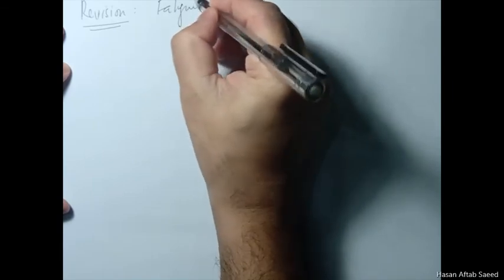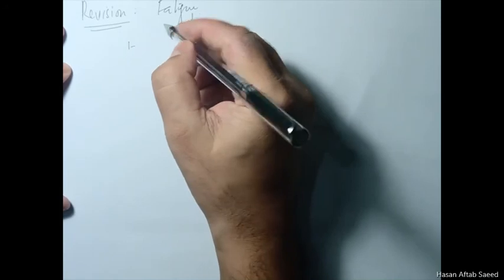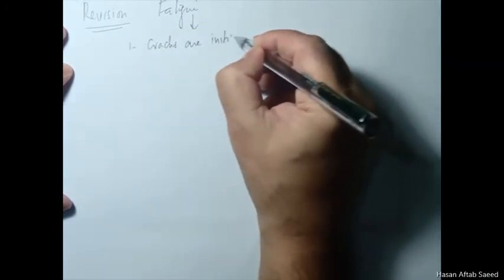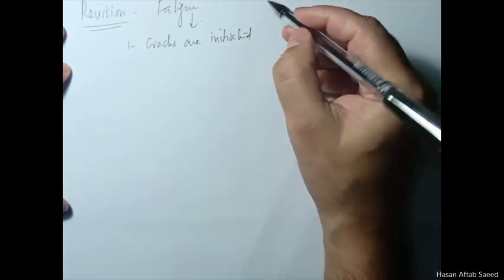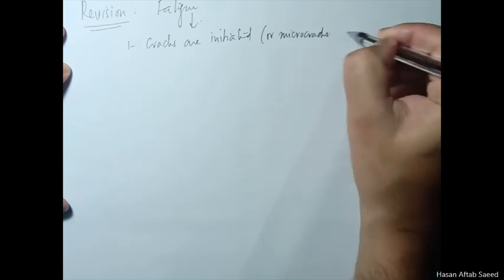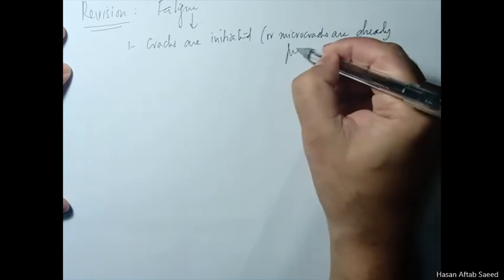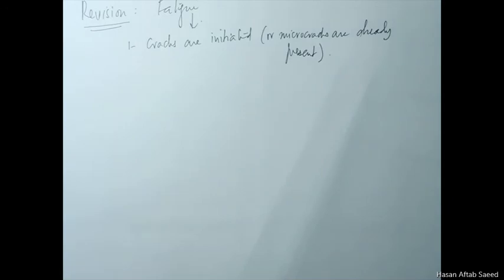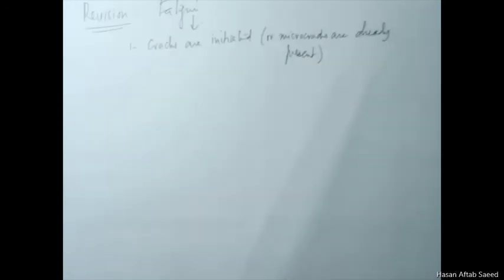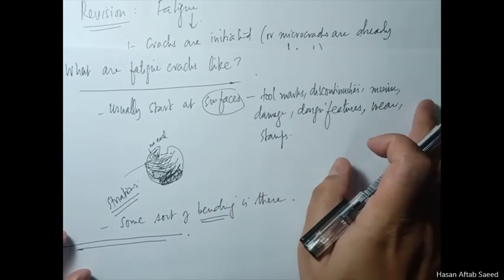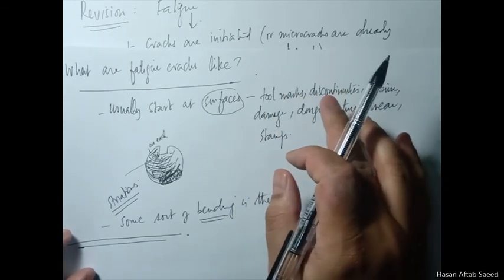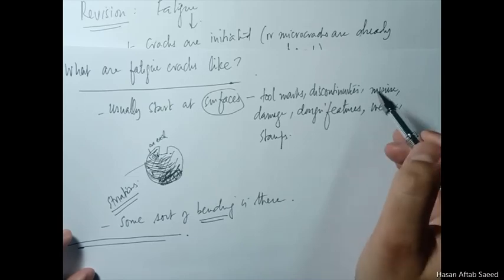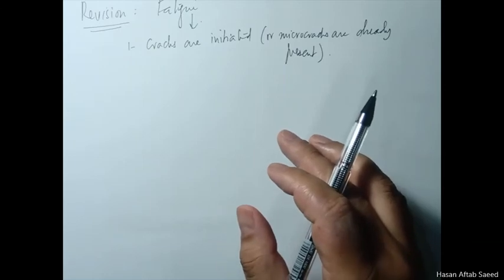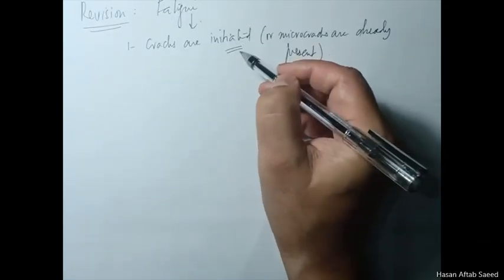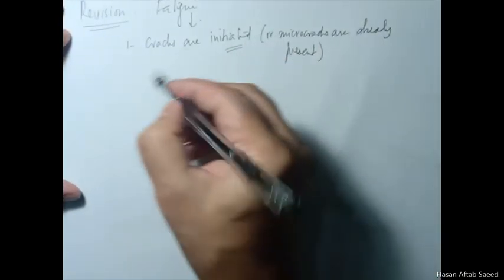What is fatigue? Where does it fit in? Fatigue. The process is something like this. Cracks are initiated or micro cracks are already present. All materials will have some sorts of micro cracks or defects. So cracks are already there, but even if they are not there, we have just discussed that even if something is perfect, no cracks, you have polished it, still at some discontinuity, at some design feature, at some point during use, if not during fabrication or assembly, they'll be initiated at the points where there are stress concentrations, and then they'll grow. Or in other cases they are already there from the start, but they are obviously subcritical crack lengths.